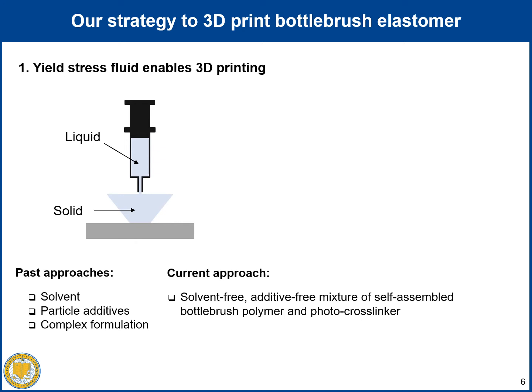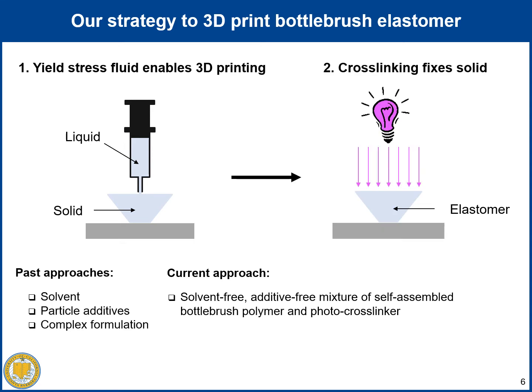Instead, our approach is by leveraging the self-assembly of bottlebrush polymer to induce the yield stress fluid behavior without either solvent or particles. Then, mixed with a small amount of previously demonstrated photo-crosslinker, the 3D printed soft solid can be transformed to a bottlebrush elastomer after UV curing.